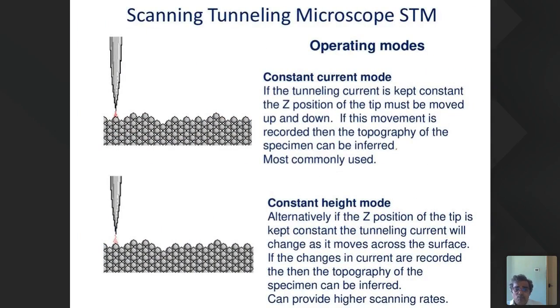There are two types of modes of operating the scanning tunneling microscope. One is constant current mode, which is most widely used. Here, the tunneling current is kept constant. The position of the tip must be moved up and down, but the current is kept constant. This movement is recorded, then the topography of the specimen can be inferred based upon the varying height. Because to maintain the current constant, the tip has to move up and down. That movement will be recorded, then the topography can be inferred. The other counterpart is constant height mode.